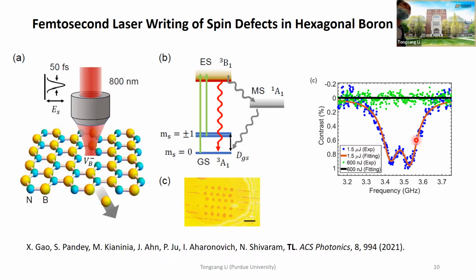What happens if we use a different wavelength? You mean this one? Yeah. This wavelength? They may have some effect, but I don't think it will have dramatic effects. Will we create both boron and nitrogen vacancy, or just one? In this paper, we mentioned that it really depends on the laser peak power. If the peak power is not in the correct range, we create a lot of defects but don't get this ODMR. So we need to choose the correct energy range.